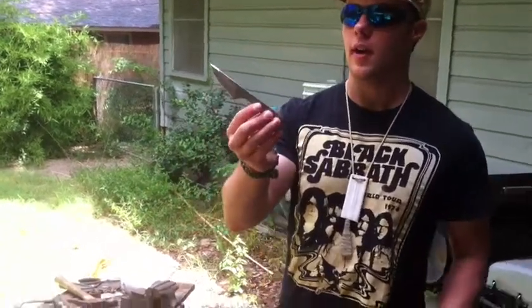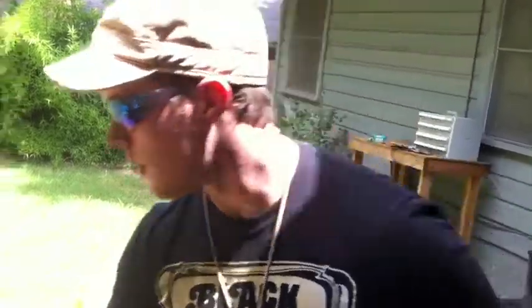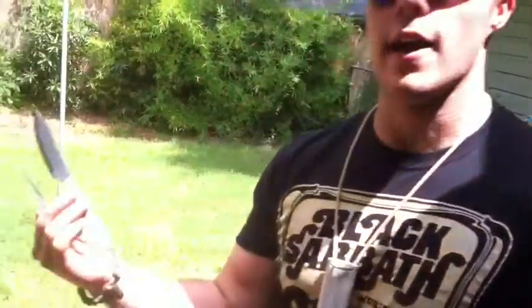This is one I made back in December and it really doesn't represent the quality of knife I make anymore. It's heat treated in a similar manner as these newer knives, but the difference is in the temper. Instead of treating it for an hour and then letting it cool and then doing another 35 minutes, I tempered this one at an hour, let it cool, and then tempered it for another hour. So it should be a little softer than the knives I do now.